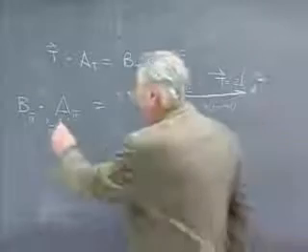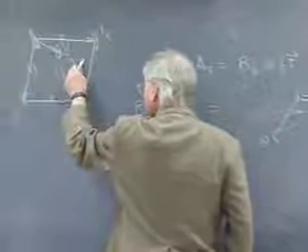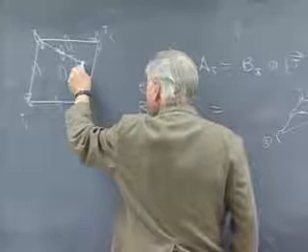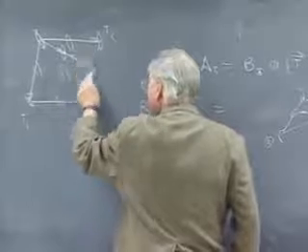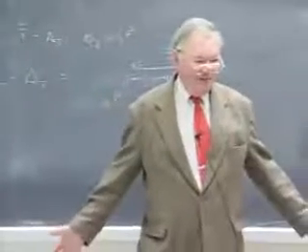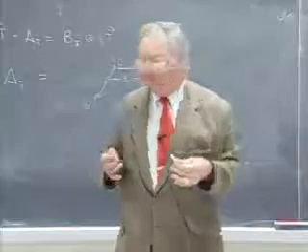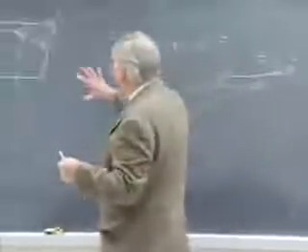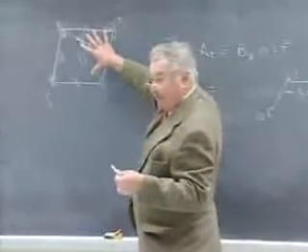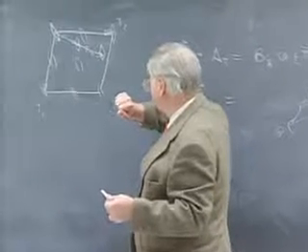So in other words, if we put a twofold axis down in this place in addition to the ones that we already have, we have created in the base of the cell a new twofold axis in this location that just mucks everything up, because it's going to rotate the translations that we have, it's going to rotate the twofold axes that we have, and we will not any longer have a group. We will not have a set of operations that closes upon itself.